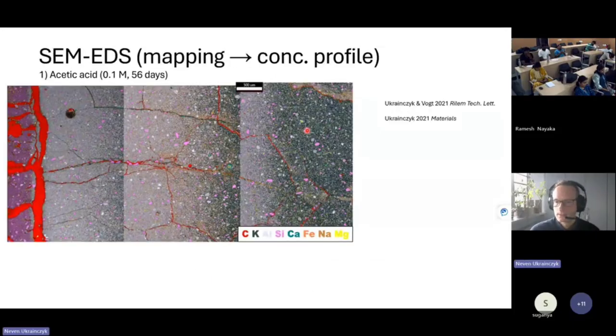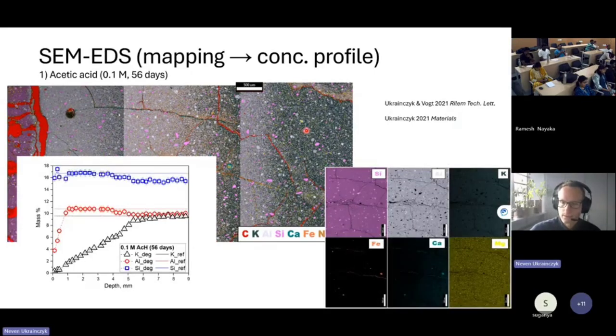So here you can see the cracks and acid attack, and with this chemical analysis, we can do the EDS mapping, and then analyze the concentration of potassium, aluminate, silicate in depth. This is after 56 days in 0.1 molar acetic acid. This is just a paste. You can see quartz particles, but they are part of the clay. Quartz is inside, but this is still paste. And you can see here how the potassium is leached out, and here on the surface we have dealumination of the geopolymer.